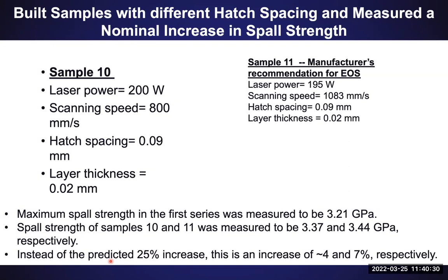So once we determined what we needed, we basically went back to Dan Toma, to basically Wisconsin, and said, hey, can you build us samples that have these combinations of the build parameters? So they built us 2 extra samples. Sample 10 had the hatch spacing we requested. And for fun, they also built us another sample, which was actually the manufacturer's recommendation for the EOS machine that they were using.